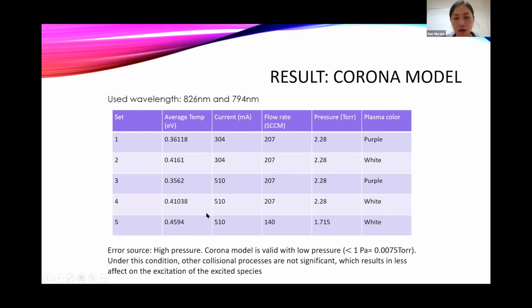And the temperature we got from the corona model was lower than we expected. We were expecting that arc plasma's electron temperature is going to be about 1 eV to 10 eV. However, we got about 0.3 to 0.4 eV. And we think the reason of this big error is high pressure. We use 2.28 torr and 1.715 torr.